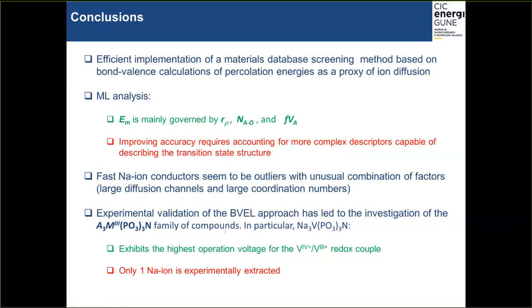For example, from Elise Nanini Mauri, how can the system, meaning active material and electrolyte, be taken into account from the calculation phase? Well, in this case, we only focus on one material, the electrolyte or the cathode. So we only look at the ionic conductivity in the bulk of these two components. We, at the moment, have not gotten into the problem of describing, for example, the interfaces that form between these two components. So our approximation would be to compute with this technique only the ionic mobility in the bulk of a solid electrolyte or a solid cathode material.